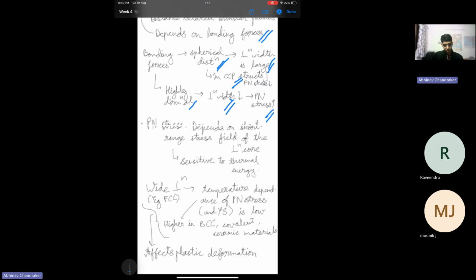Now, PN stress depends on the short range stress field of the dislocation core. So same thing which I told earlier. In a very localized region, what is the stress field or distortion that has occurred in its environment? And so this will be sensitive to the temperature. If the temperature is higher, then the intrinsic thermal energy or vibrational energy of the atom is more. So that can be utilized to fulfill the activation energy required for atomic jump to occur, and the dislocation to move. So PN stress will be lower if the temperature is higher. It is also called